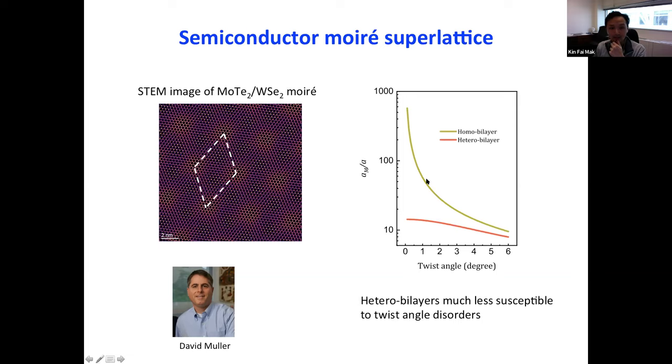And I think in that sense, there may not be much of a difference between twisted bilayer graphene and this material. Actually, it may be even worse in this material because the lattice is softer, right? The Young's modulus is smaller. So in terms of lattice relaxation, it may be even more significant in this material. It really depends on how big the moiré period is. Okay, thank you. Overall, all the structures tend to expand the more stable stacking structure compared to the less stable stacking structure. So a rigid lattice is really a crude approximation. And in all moiré materials, basically, you have certain degrees of lattice relaxation.